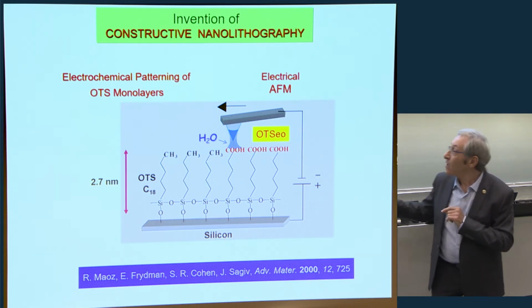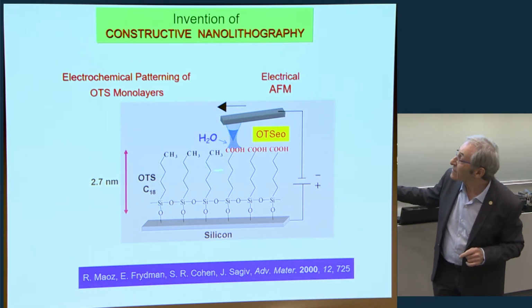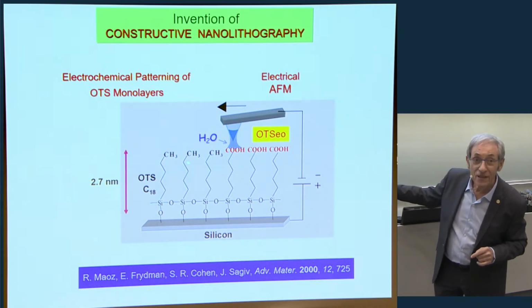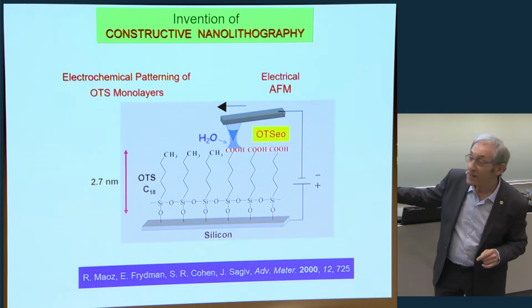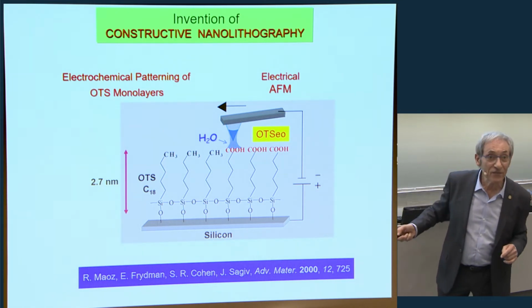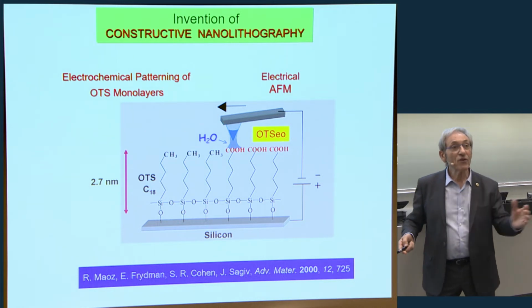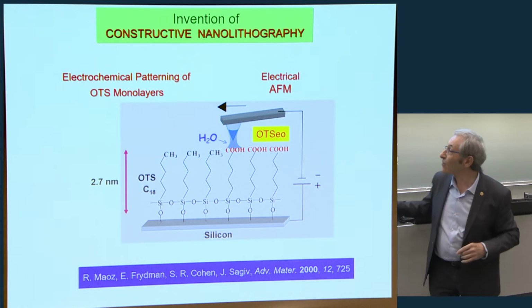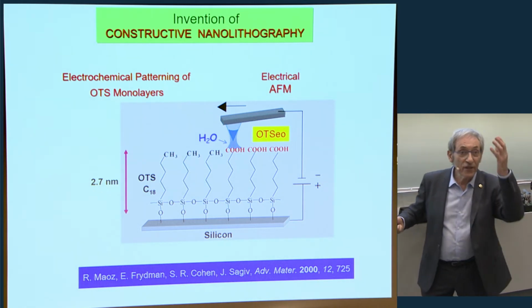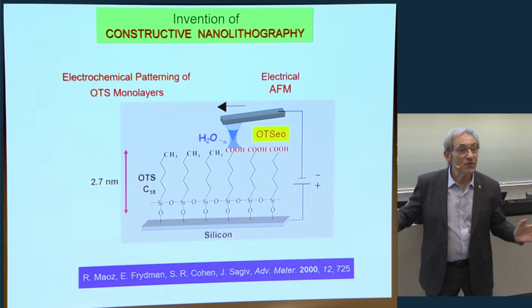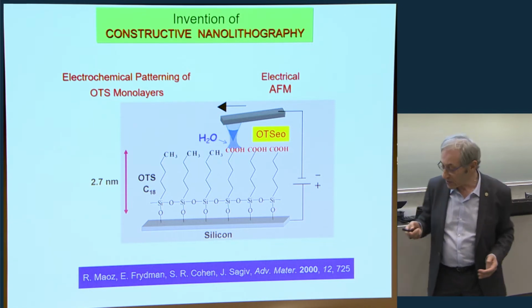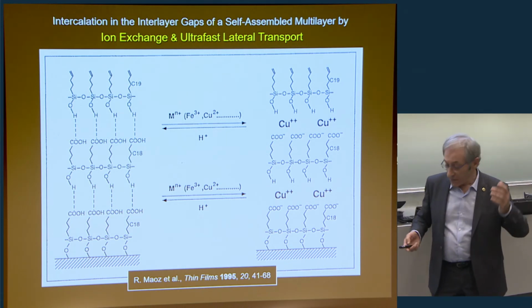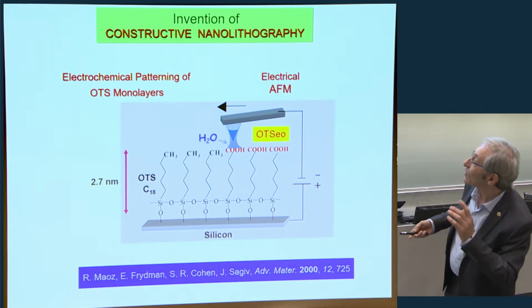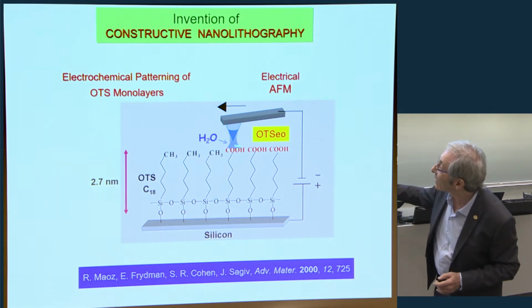Then we'll see why. Because this is the only method that doesn't create any defect at the interface between functionalized and non-functionalized. The structure is totally preserved. You only convert CH3 to carboxylic acid. And this is very important because if we have to place electrodes here, if you have a defect, you have leakage. And it's no longer possible to use it for any electrical applications. So, just a moment. We have now carboxylic acid.